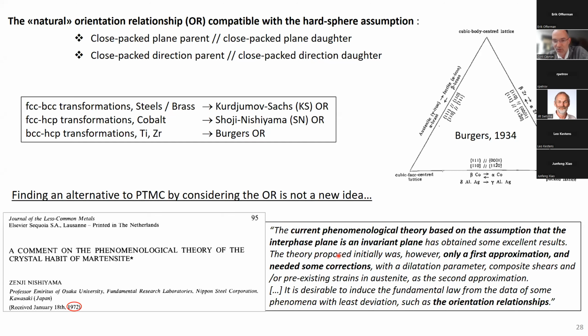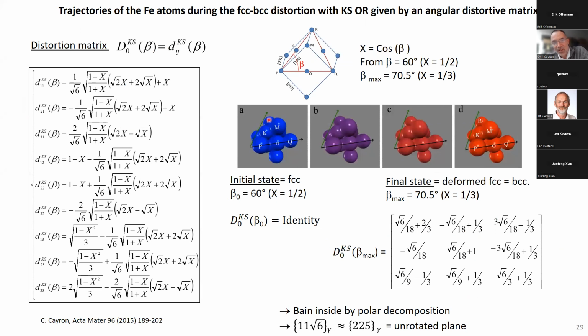Let's assume that we know the orientation relationship. And for example, here between the initial phase FCC and the final phase, which is distorted FCC, it's BCC, I assume a Kurdyumov-Sachs orientation relationship. It's an assumption. And I also assume that the atoms, iron atoms, are hard spheres. And then I can go from FCC to BCC continuously. I just have to open the angle between the two dense directions. Here it's the 110 directions of the FCC phase that will become the 111 directions of the BCC phase. I open this angle from initially 60 degrees to 70.5 degrees.